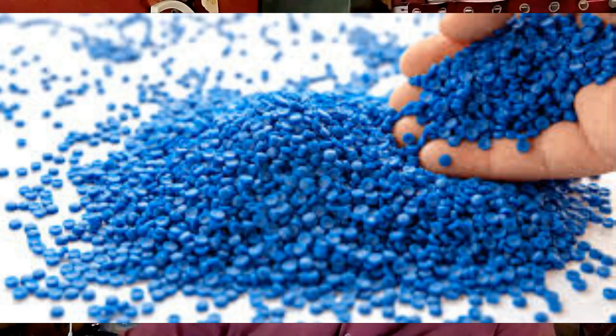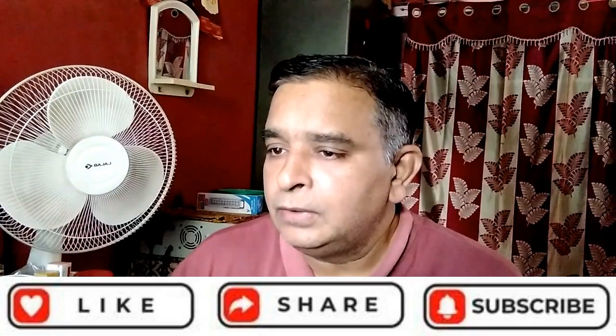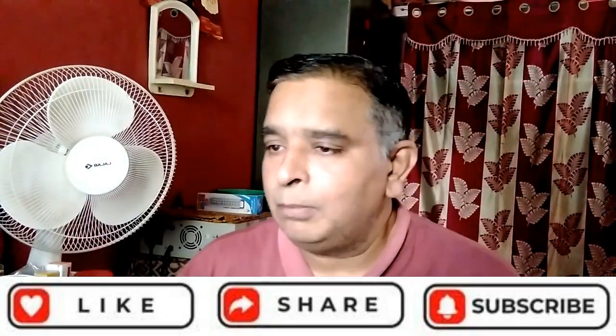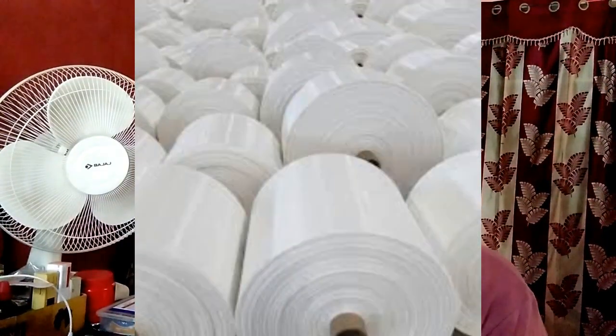Next point is, how is polyethylene produced? LDPE is prepared from gaseous ethylene under very high pressures up to 350 megapascals or 50,000 pounds per square inch, and high temperatures, that is up to about 350 degrees C, in the presence of peroxide initiators. These processes yield a polymer structure with both long and short branches.